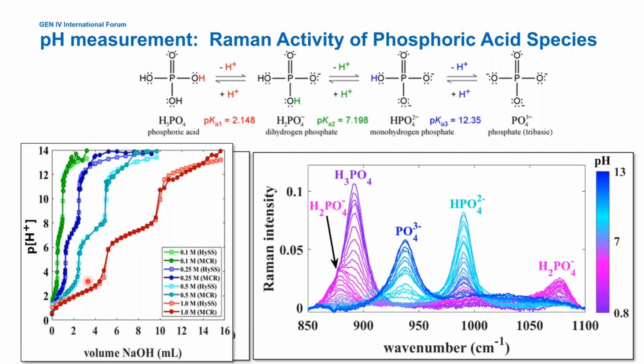And as we titrate, the Raman model is predicting, or measuring, the pH. And we compare that with the light red symbols, which are the theoretical calculation for the pH in that solution. So we were spot on with the theoretical pH for that solution with each one of these. And we can do this not just at very high concentration, but also in very dilute concentrations of phosphoric acid. We're spot on with the theoretical calculation.